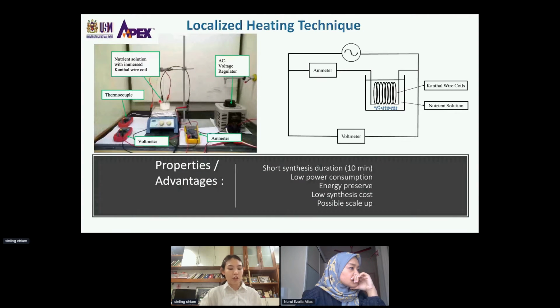First, the precursor solution is prepared. Then a benchtop power regulator, which is an AC regulator, is used to pass the electric current to the wire. Since the wire is submerged in the precursor solution, the heat is transferred directly and rapidly into the target solution. By this, the heat loss can be minimized. In this study, the particles formed after 10 and 15 minutes will be collected for characterization and application.